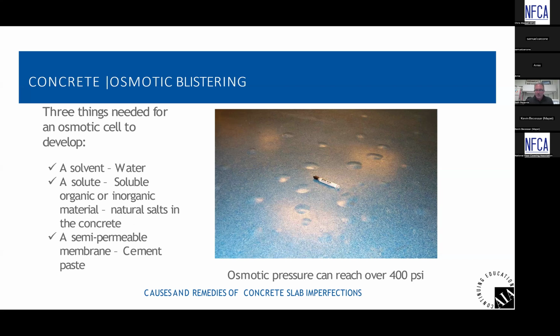If that makes sense. And all concrete, correct me if I'm wrong, but all concrete comes highly alkaline, at least 12 on the pH scale. It does. And then when it starts to cure, and the water is chemically bound and evaporated out, the carbon dioxide in the air starts to react with the surface of the concrete, which will typically carbonate, and it reduces the pH at the surface, typically down to maybe a 9, 10, something like that.